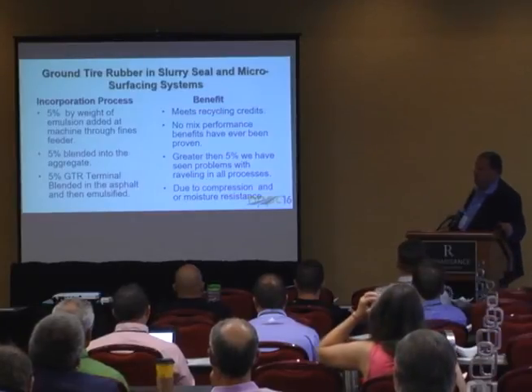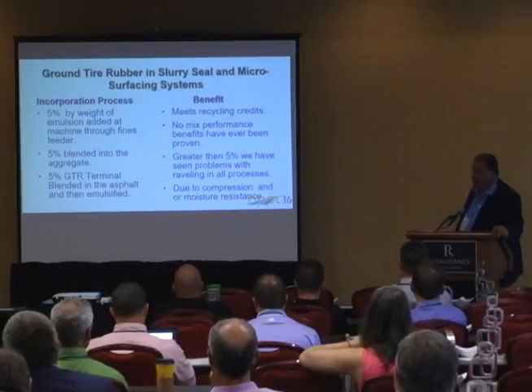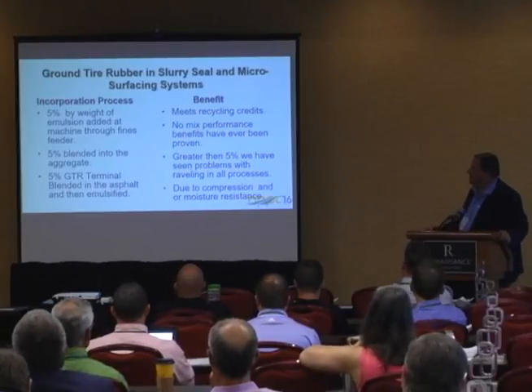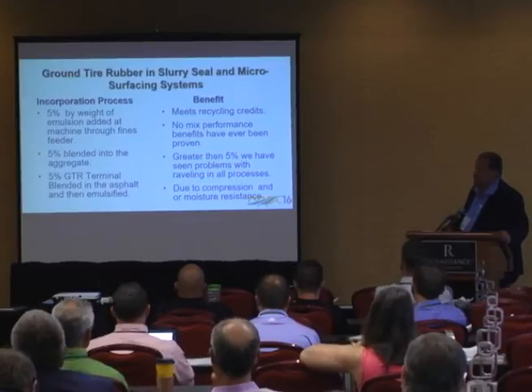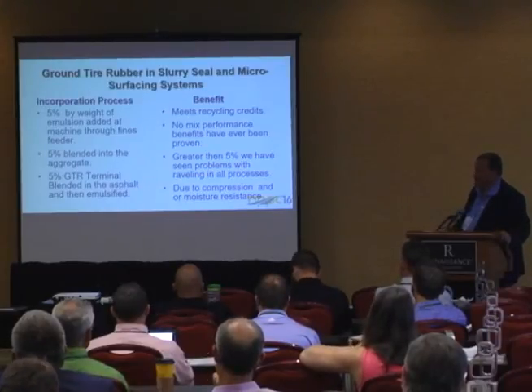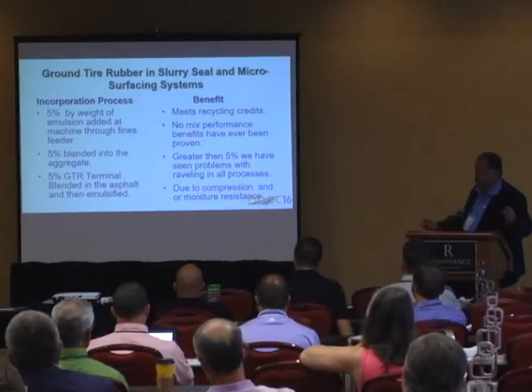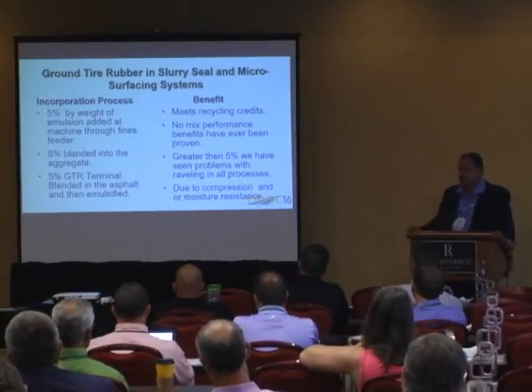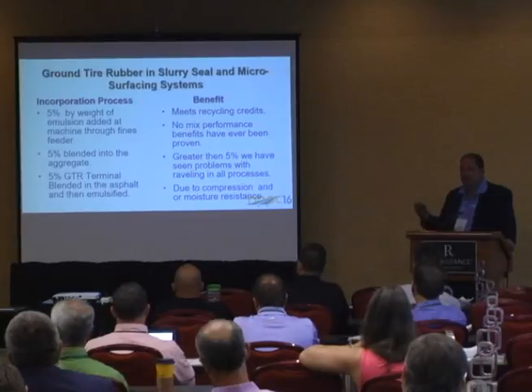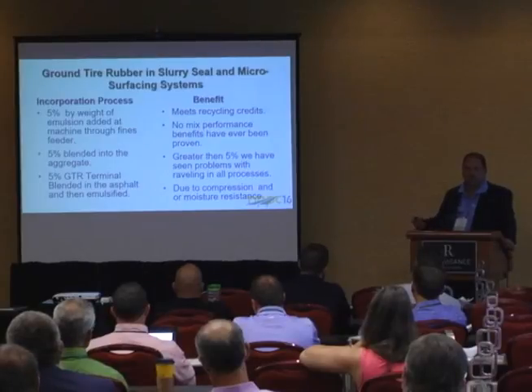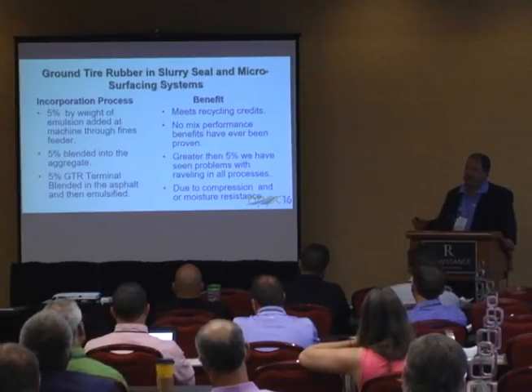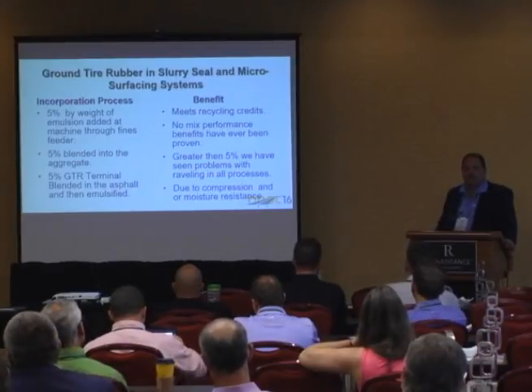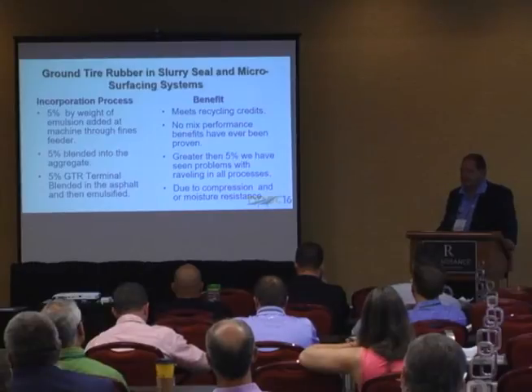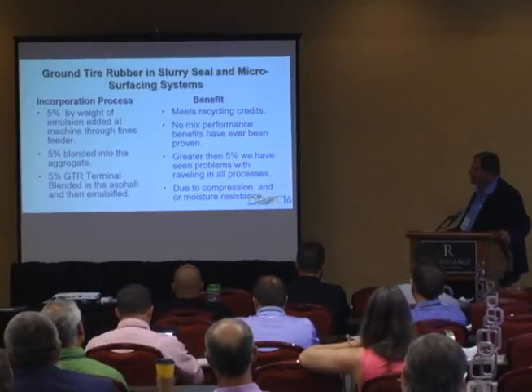So here are 3 ways in slurry and micros that we are doing currently throughout the state. We have 5% by weight of emulsion added at the machine through an extra fines feeder. We have 5% blended into the aggregate. We have 5% GTR, which is a terminal blend asphalt, being blended into the asphalt. So you've got 3 ways of getting it there. LA County, San Bernardino County, Riverside County, and San Diego County all consider all 3 methods acceptable and legitimate methods of getting it in there. So there's no proprietary issues around that. It's whatever the contractor's choice is, but here are 3 options.